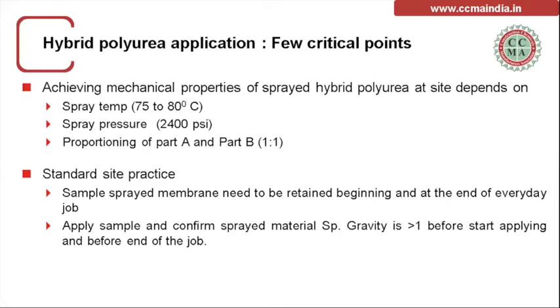Sorry for that inconvenience. So it has to be sprayed at 75 to 80 degree temperature. And then the next important thing is the pressure; the spray pressure goes at 2400 psi. If there is any variation in this, apart from the mixing proportion of 1:1, then the end result of the sprayed membrane will not be equal to what the technical data sheets claim. So we have to be very, very careful.